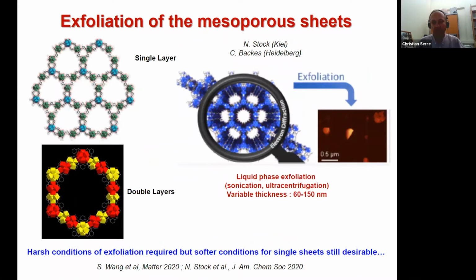Of course, these materials are 2D. So at the time when we made this sample, we were wondering if this could be exfoliated, but we had no time to do that. And our colleague from Kiel, Norbert Stock, reported almost in parallel to our paper a similar structure, but with an amide functional group. It's not presented here, but it's an amide group.